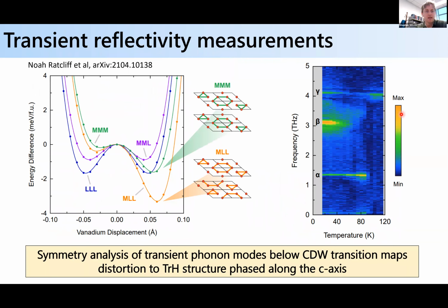Okay. And so more recently, John Harter's group here at UCSB has done some transient reflectivity measurements where they looked at a larger unit cell than we did. Basically, they looked at a 2 by 2 by 2 unit cell. And then they looked at the transient reflectivity. So they basically looked at the reflectance as a function of time after being hit with a pump, sorry.